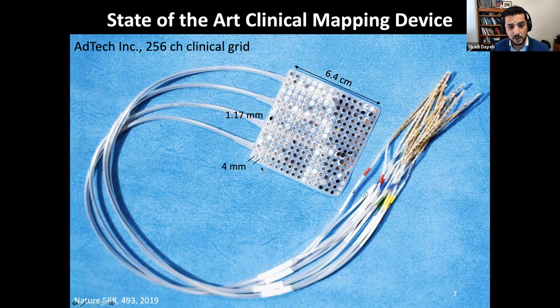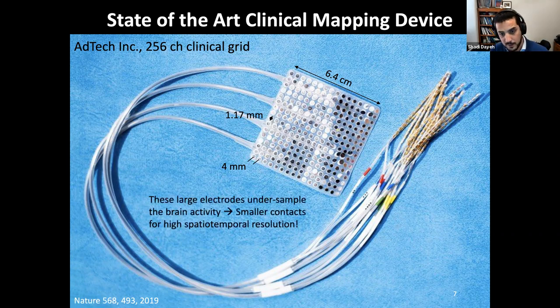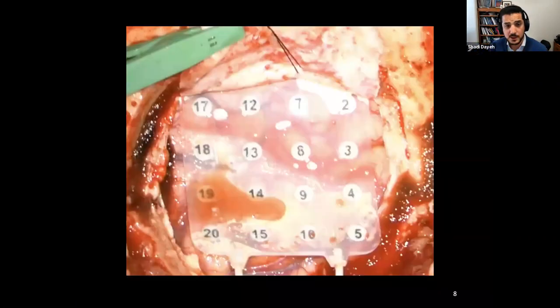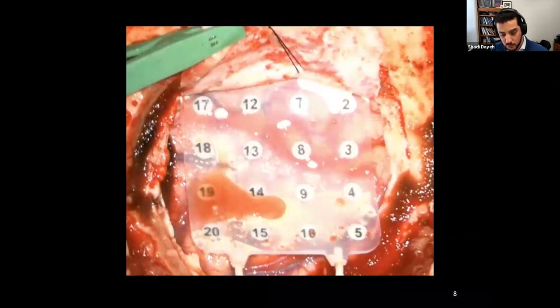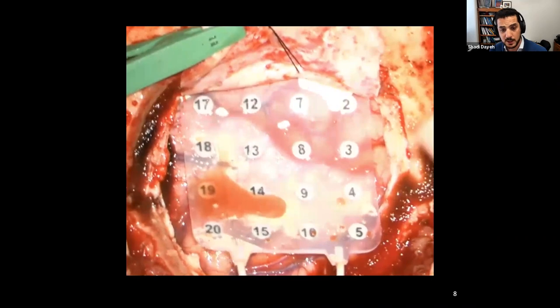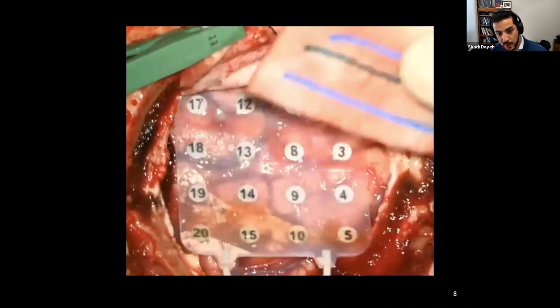Now, for this type of application, what has been used is a grid composed of 256 contacts. And this is built on 0.5 millimeter thick silicone layers. And they are 4 millimeter apart, and each contact is about 1.17 millimeters. So this greatly undersamples the brain activity from the surface of the brain. If we want to increase the spatial resolution and make these contacts smaller, the impedances of these electrodes will start to rise, and that will compromise the recording capability of these grids. So, we pursue techniques to improve this in terms of the electrophysiological or electrochemical interface.